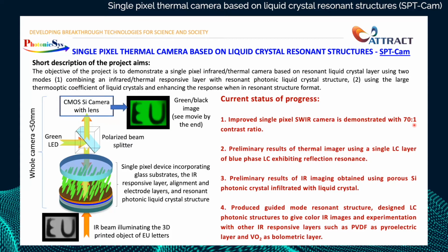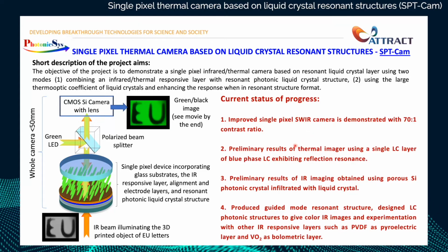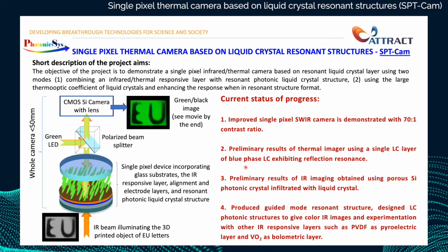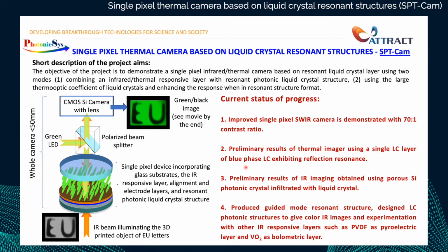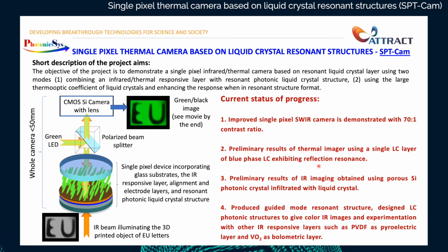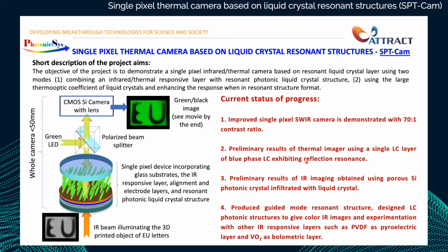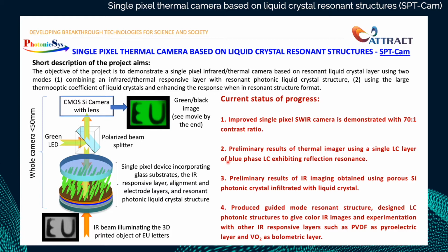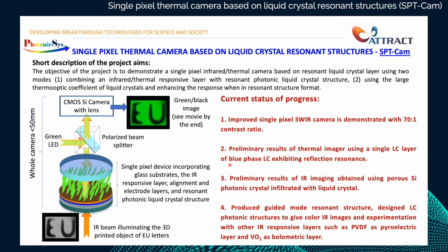We also progressed in thermal imaging using a single liquid crystal layer based on a blue phase liquid crystal, which is already resonant because it exhibits what's called a selective reflection peak, and it's highly sensitive to the temperature. So by shining infrared light on it, the temperature variations of the written image will be read with the visible light.